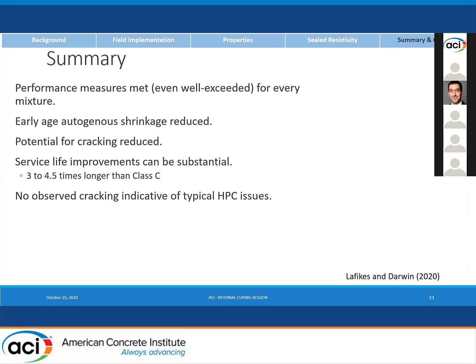So just very briefly, the summary is that indeed these mixtures perform quite well. The early autogenous shrinkage was reduced from internal curing. The potential for cracking was significantly reduced. We've estimated that the service life improvement can be very substantial. We should be able to target the 75+ year design life. And we didn't see any cracking that was indicative of typical HPC issues.